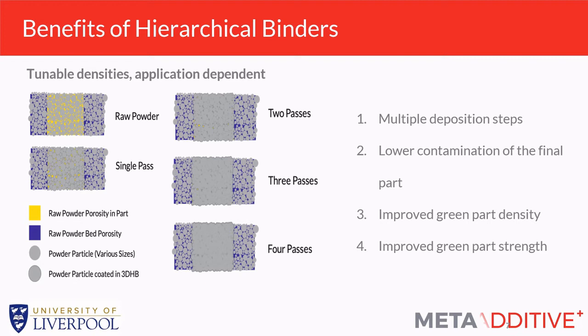But really, I think the biggest benefit probably is this improved green part density and green part strength. Because you're infiltrating and binding simultaneously, the density and the strength of the component as it comes out of the printer, before it's even had a heat treatment, is much higher than conventional binder jet. That means that we could perhaps print larger components, and components that don't need support structures or as many support structures, because they've got that integral strength already.